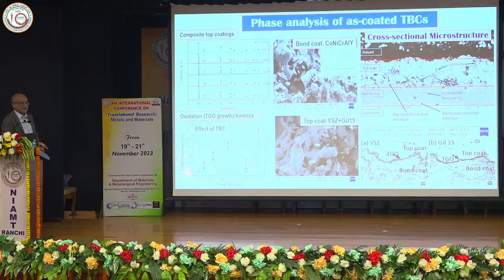So basically, this is zirconia alloyed with Gd2O3, and these are the phase aggregates. This is how you measure the kinetics of the oxidation. Oxides won't oxidize, but at this interface you have the thermally grown oxides. If you look at their growth rate, that gives you an idea as to which way the interlayer is oxidizing.